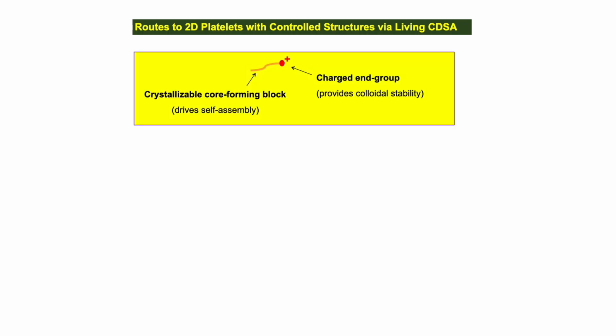And the way you do this is you make again an amphiphilic structure, so one that has a charged part or polar part and another part that's non-polar. We use a polymer that will crystallize for the core forming segment, and then we have a charged group which dissolves in the solvent, and this is what allows you to make colloidally stable micelles, so they're stable in solution.